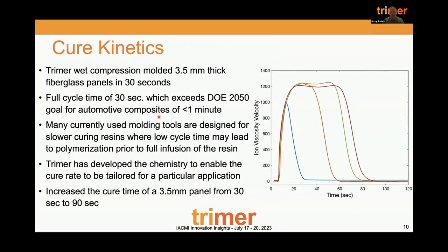And so what we did is we've developed the technology to latenize our resin to provide tailored cure rate. So that's shown in this plot on the right. What we have is 3 different resin systems here with different sets of latency. And what you see is this upslope is the same in all of these. So this is the press closure, viscosity drop. It's a little higher in these more latent systems because the temperature is allowed to progress further. But we have a plateau in these materials. And that plateau is where the material sits at a very low viscosity before it snap cures.